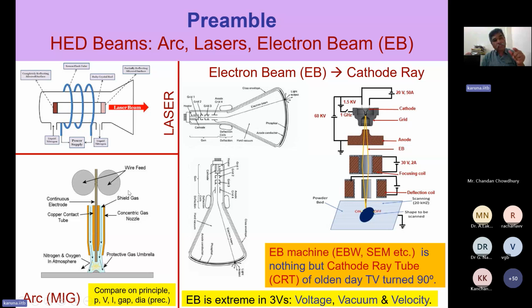So, whereas the voltage here is of the order of 150, sometimes for fine welding we go down to 20 volt also. Okay, current can be up to 20 amperes. Otherwise, there are situations like electroslag welding where they've gone up to 1000 amperes easily. Okay, so this is a system which is low voltage, high current. On the other hand, electron beam is a system which is high voltage and low current. Okay, this is the basic difference. Low voltage, high current; high voltage, low current.